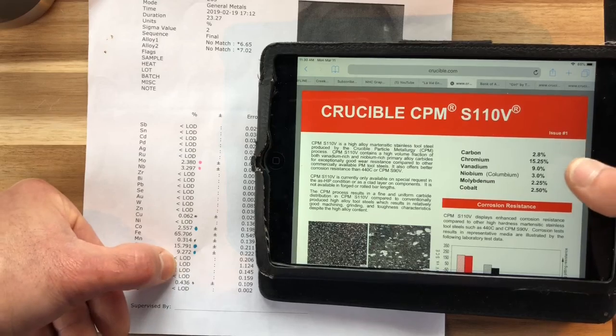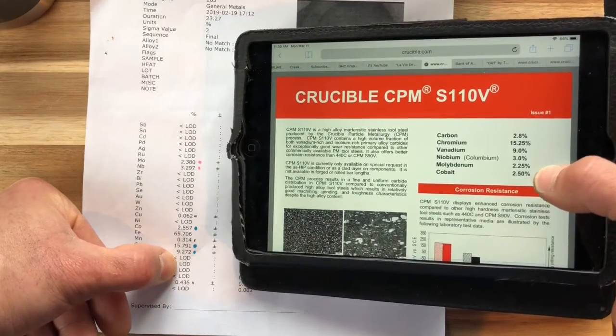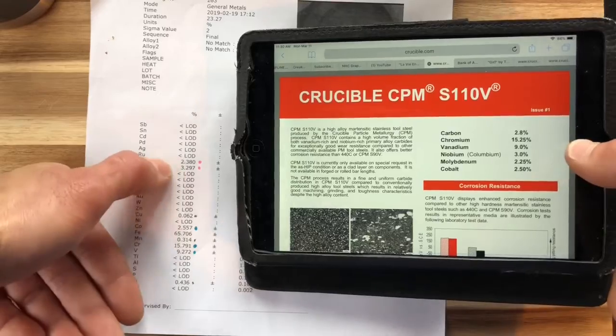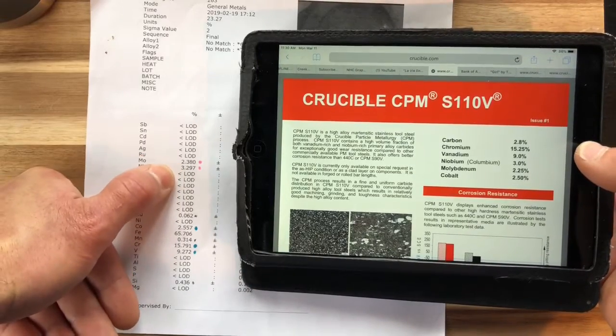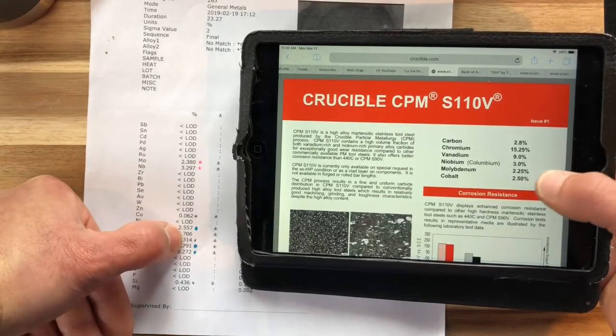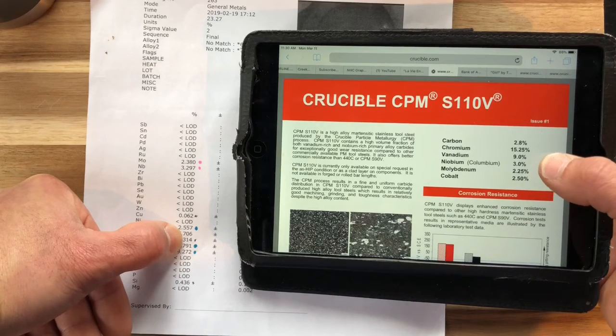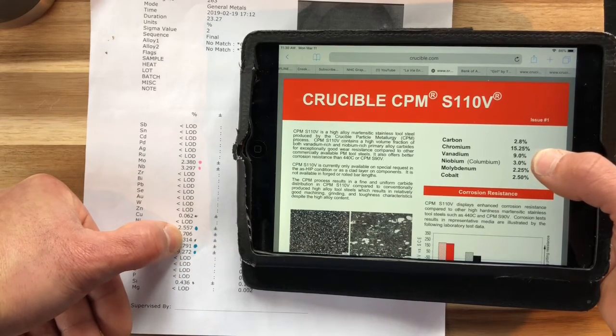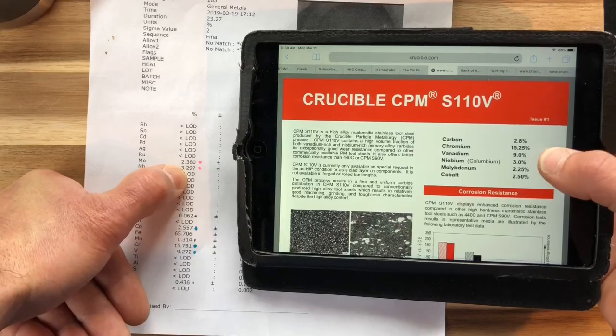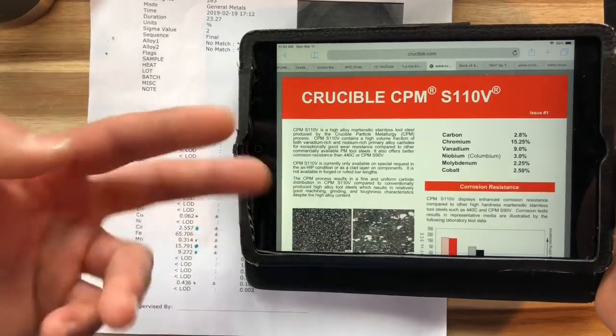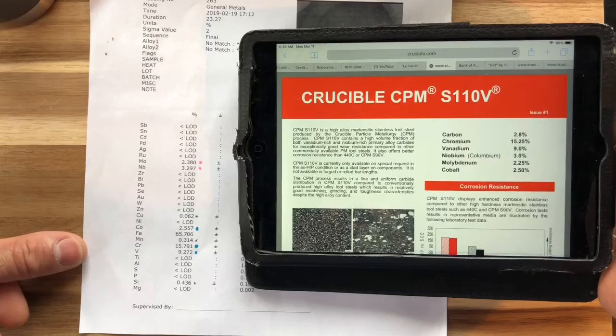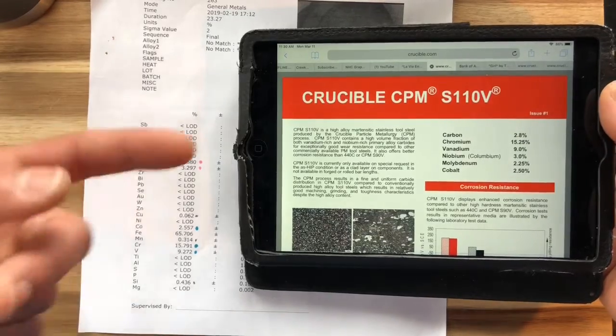Now, vanadium is still high at 9. It's at 9.2. But see, here we got molybdenum a lot lower and cobalt a lot lower. These are actually more in line with what we're seeing here. The cobalt's right about where it was. But yeah, see, niobium's at 3%. That's a lot closer to what we have here. So that's where I'm saying you got to kind of cross-reference and make sure that your information's correct. But yeah, so as far as the makeup of this, I'll show you guys the PMI gun shooting the S110V PM2.